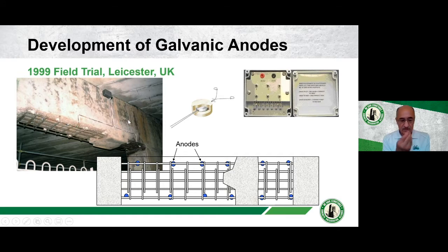The whole structure was repaired in the same way, so we had a load of patch repairs all around. Each one of them had galvanic anodes inserted, but those were just connected directly to the steel reinforcement with these tie wires that you can see here. In this case, because we wanted to monitor it, we cut off the tie wires apart from one. We attached a lead to that and took it out into a junction box, and from the junction box we then connected to the steel reinforcement at several places to ensure continuity. And all we had to do then was carry out the repair and then monitor the performance of the anodes.